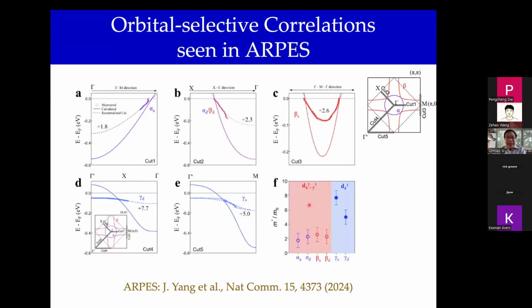So let's dive a bit into more details. This is the ARPES measurement of Xingjiang Zhou's group, and these are cuts in the Brillouin zone that you don't have to pay too much attention to, but the point is that one can probe the dispersion for this inner pocket, which is primarily 3d x square minus y square orbital contribution. And one could take the cuts that are probing primarily the